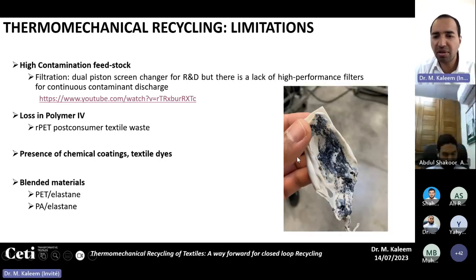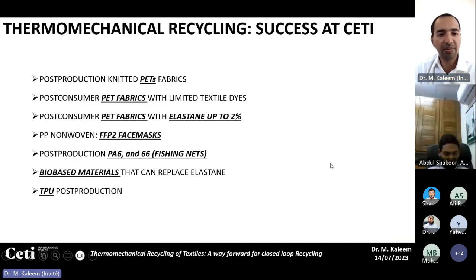So this is the filter that I took from the Erema line, the thermomechanical recycling. You can see that the filter is highly contaminated and can block the process. If you don't change the filter continuously, then you cannot recycle this material. So you have to continuously purify the melt stream in order to get good quality granules afterwards.